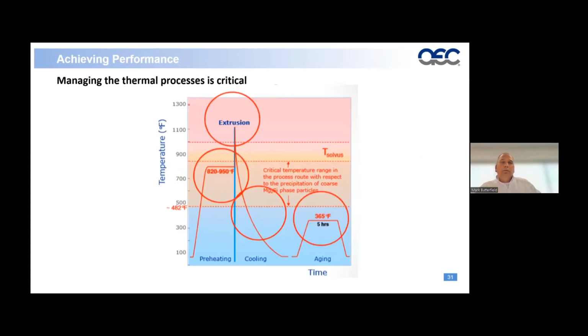So the thermal process is critical, as you can see, and kind of what we just talked through. It goes through a lot of variation, a lot of heating and cooling. The first phase there we see is the heating of the billet. Then the extrusion process generates a rise in temperature within the product that's engineered and required to meet the material properties. Then we go through a quenching process.